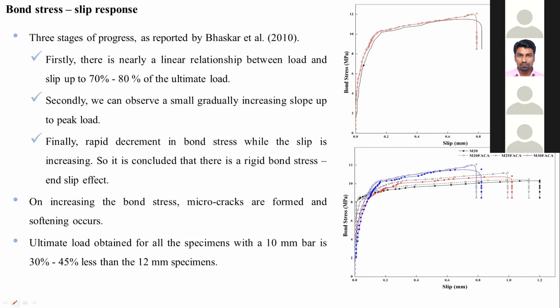That means firstly, up to 70 to 80%, there is a linear relationship between load and slip. Secondly, there is a gradually increasing load slope. And the third phase is the failure phase, that is a rapid decrement in the bond stress.